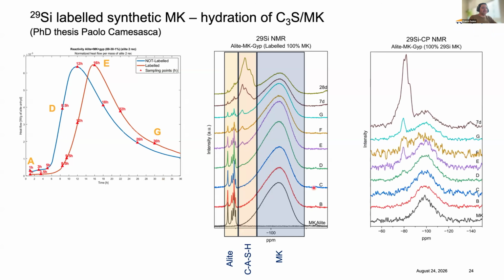The other thing that has been very enlightening from this is that by doing CP analysis, cross-polarization, where you transfer magnetization from protons into the nuclei of interest, in this case silicon, you can see which silicons are neighboring protons, and we can see actually that the dissolution of metakaolin occurs from this left side of the hump, which is the side that we believe is closer to the surface.